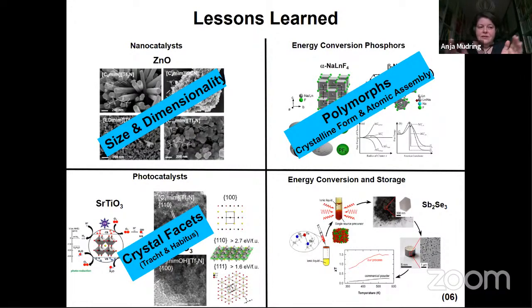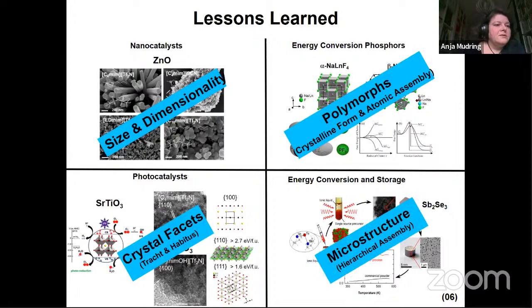and make it nanostructured in such a way that the electrons can travel freely, versus the phonon gets scattered at the grain boundaries. And that again, you can control with the ionic liquid, as you can determine both the size of the particles that are forming as well as their aggregation. So here ionic liquids are also extremely powerful.